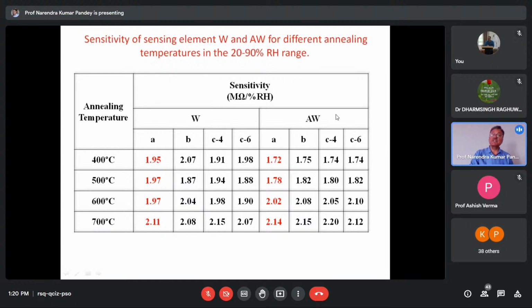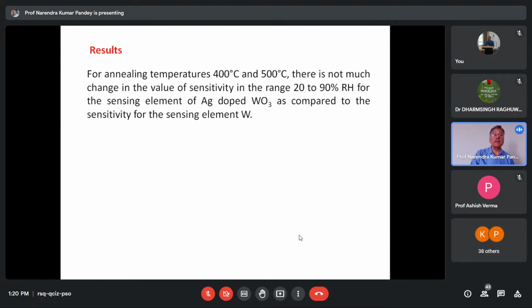And similar experimentation for Ag doped WO3: initial increasing cycle, decreasing cycle, increasing cycle after 4 months, increasing cycle after 6 months. You can see here that for 400 to 500 degrees centigrade, the change in sensitivity from pure WO3 to Ag doped WO3 is not much. But if the annealing temperature is 600 and 700 degrees centigrade, then there is a significant change in the sensitivity, and that we can show over here.